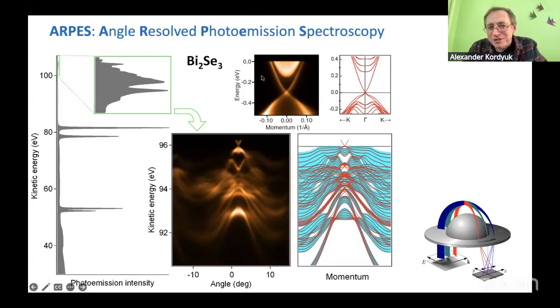And therefore, here you see this white feature. It reproduces the bulk band, and the thin feature reproduces the surface band. Not always, because some bands could also be very two-dimensional even for the bulk. But I said that for a normal compound, if you want to distinguish experimentally between bulk and surface bands, you should just contaminate the surface a bit, and then bulk states still exist, but surface states disappear.